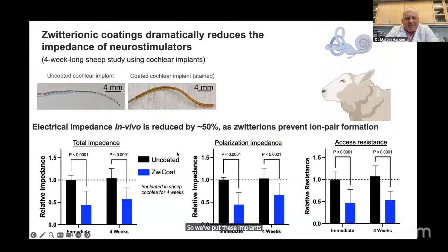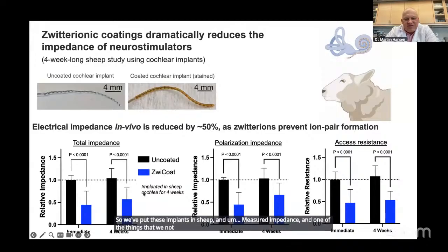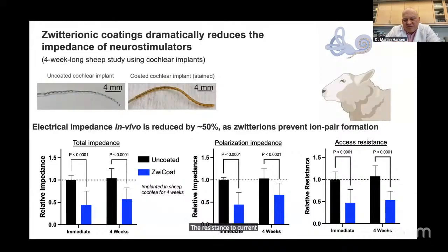So we've put these implants in sheep and measured impedance. And one of the things that we noticed is that not only does it reduce the impedance long term, but it actually has an immediate impact on current flow from the electrode arrays. So it reduces the resistance to current flow by 50% just by having the coating on there. And we think we understand how that works.